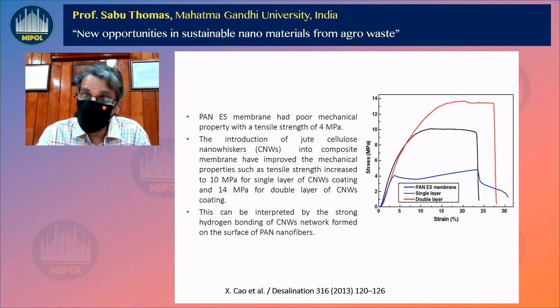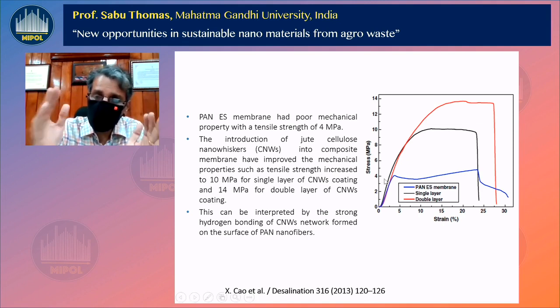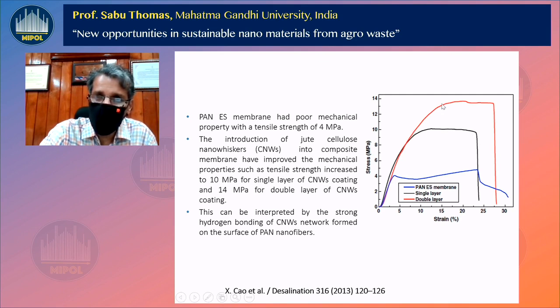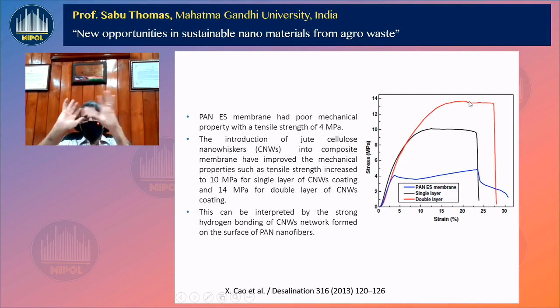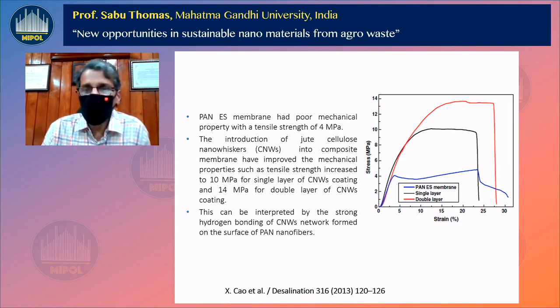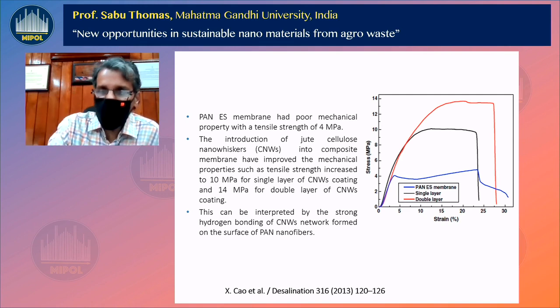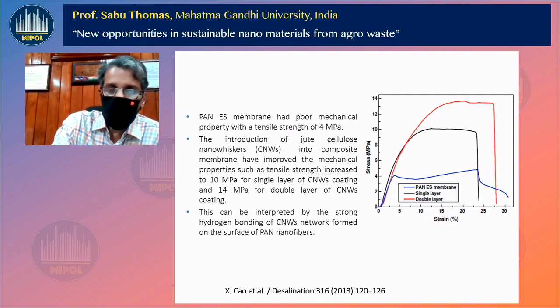Dear friends, we want to increase the strength of this material. You give a coating with nanocellulose. Look at this one-side coating. The strength becomes 10 megapascal. With both-side coating, the strength becomes 14 megapascal. So you can increase the strength of commercial filters by coating with nanocellulose.